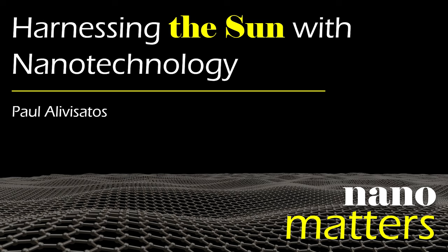We're working on two things that I'm really excited about right now. One of them concerns how we use light in energy conversion and renewable energy conversion. We are working on making quantum dot materials that can absorb high energy light and emit a lower energy light, and do that with an extremely high efficiency — almost every single time they're excited, they would then emit light. If they're excited a million times, they might only miss emitting a photon once. If we can make such a material, it can actually be used as part of a device that concentrates sunlight to a very high degree.